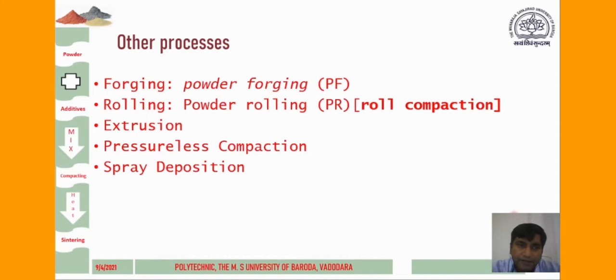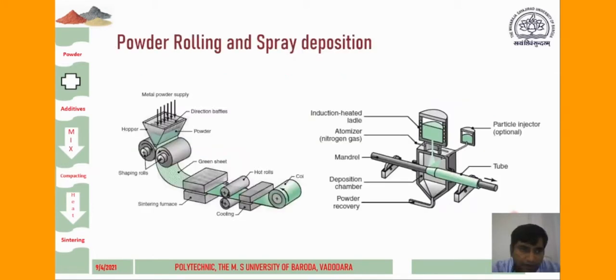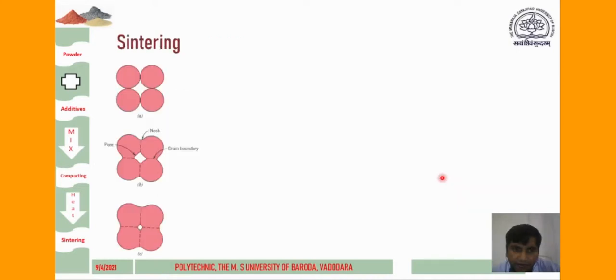Other processes that are used for compaction are forging, that is powder forging, rolling, called powder rolling, extrusion, pressureless compaction, and spray deposition. Just look at the diagrams and figures that I showed, that is a photograph. This is the hot rolls, and from here the powder is compacted. So it is a rolling process, powder rolling process. There is a base metal, and on the base metal you are rolling the powders. In another case, spray deposition. Here you have base metal on which you need to develop a very thin deposited cover coating, and this is done by hot or powder spraying method. Okay, so these are the discussions related to compaction.